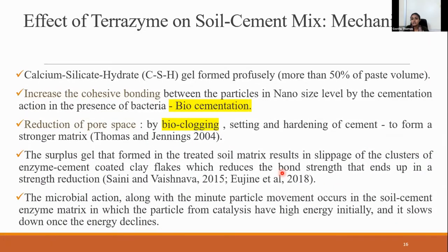The reason behind the strength improvement is explained like this. This can be concluded by two words: biocementation and bioclogging. That means in the presence of bacteria, the cohesive bonding between the soil particles is increased. This is called biocementation, and the pore voids are filled with calcium silicate hydrate gel, which reduces the pore spaces.